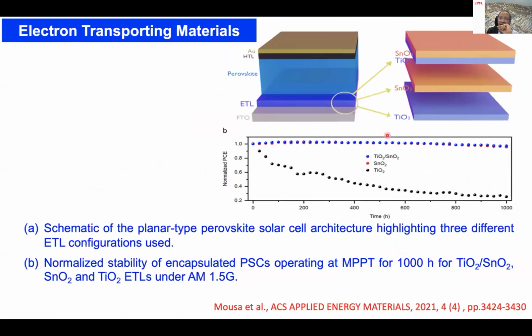So here I just want to spend some time on this. When you have TiO2 or tin oxide or mixed layers as electron transport materials, you can see the stability of these perovskite solar cells. If you have only TiO2 as electron transport material, the stability is decreasing significantly. Whereas if we have TiO2 with tin oxide deposited on top of TiO2, or pure tin oxide as electron transport material, the stability is significantly enhanced. Why is this happening? It's because when you shine the light through the ETL side, there is a certain portion, 3.5%, of UV light. The UV light is exciting the TiO2, and this excited TiO2 is attacking the perovskite, thereby it's delaminating.